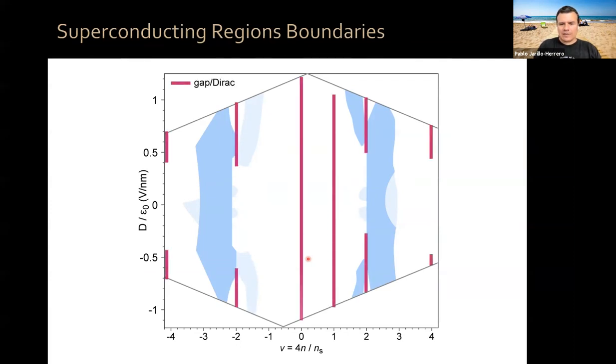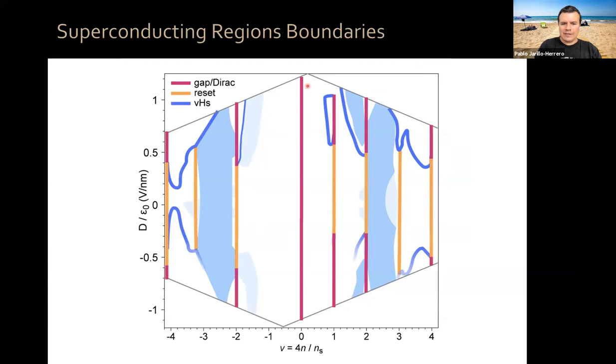So these red lines correspond to gap Dirac type of behavior, for example, charge neutrality, you remember. These orange lines correspond to reset type of behavior. And these blue lines correspond to Van Hove singularity type of behavior. And as you can see now, a clear pattern emerges, okay? At zero displacement field, superconductivity occurs mostly between filling factors 2 and 3 and -2, -3, okay? And is bounded by resets. At high displacement field, however, superconductivity is bounded by Van Hove singularities. Okay. Now, this is something which is quite peculiar. Okay, so let's examine it a bit more closely.